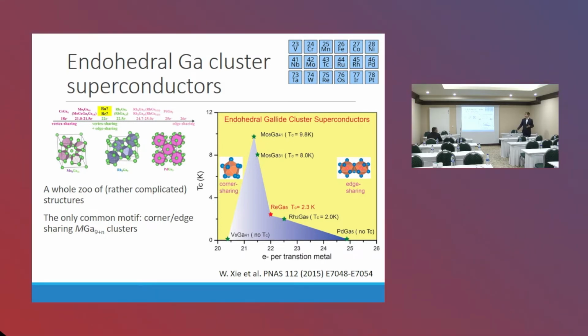Kind of exotic system with about 10 different compounds reported at the time. Most of them are superconducting. It's a whole zoo of rather complicated structures. These are just three drawn here, as just those that can be drawn in a way that you can see anything. So, for example, molybdenum 6-gallium-31 is a triclinic system with very large volume, like 136 different atomic sites.